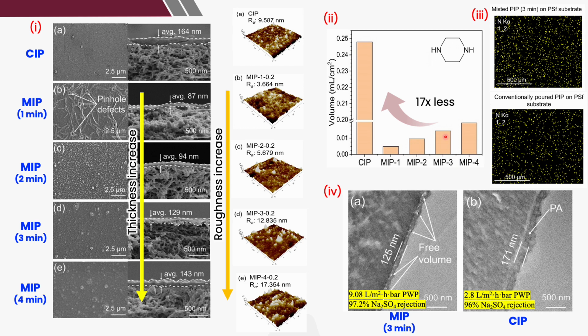We also did the EDX analysis for the MIP 3 minutes membrane surface and the conventional membrane surface. This yellow color indicates the monomer, with respect to the nitrogen. You can see here we use 17 times less chemical to form the polyamide layer, but we still have more PIP, which is the monomer, on the membrane surface compared to conventional techniques. This is the TEM image of the best MIP membrane, 3 minutes, and this membrane has a thickness of 125 nanometers compared to the conventional membrane at 171 nanometers. The advantage of this misted IP technique is that it can produce free volume within this thin layer, and this can produce a membrane with higher flux.